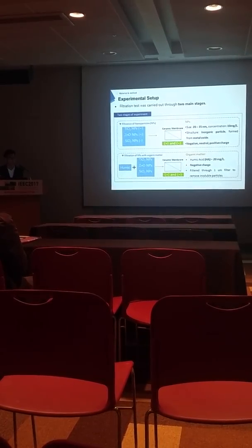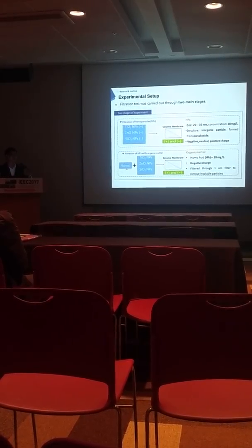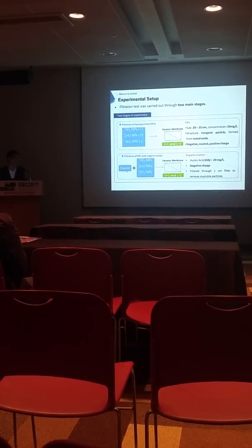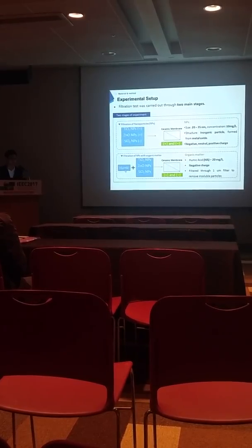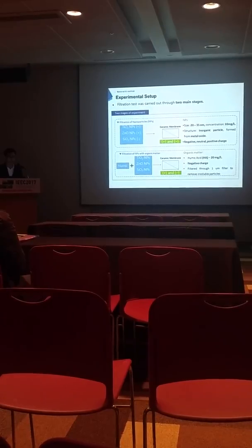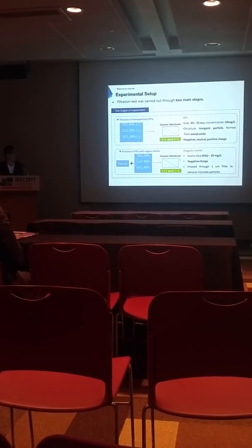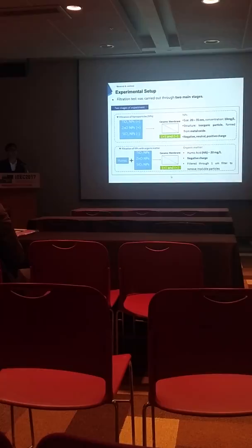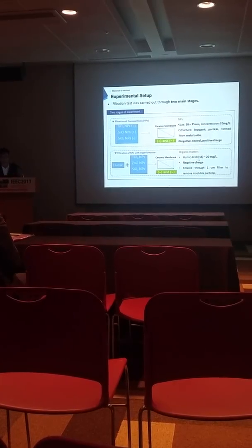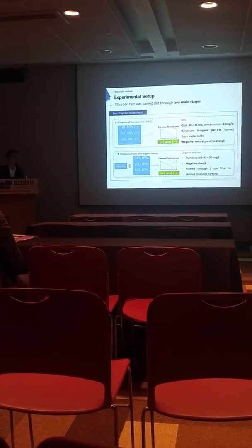At the second stage, I will add humic acid as a representative for the organic matter in the solution, together with the nanoparticles, and filtrate through the same ceramic membrane at positive and neutral charge. The humic acid concentration is 20 milligrams per liter.